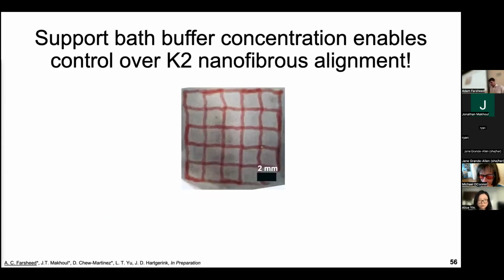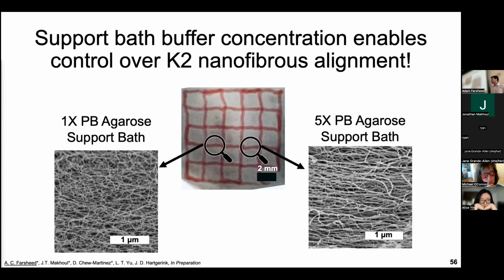And so combining this with what we showed in 2A, we tried to print into the same Agarose support baths, but in one case with 1x PB, and the second case in 5x PB. And when we did SEM, we saw exactly what we were hoping, where we saw these differences in the nanostructural alignment based on the support bath concentration that we used.